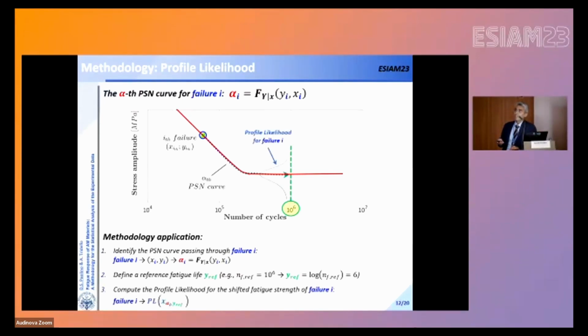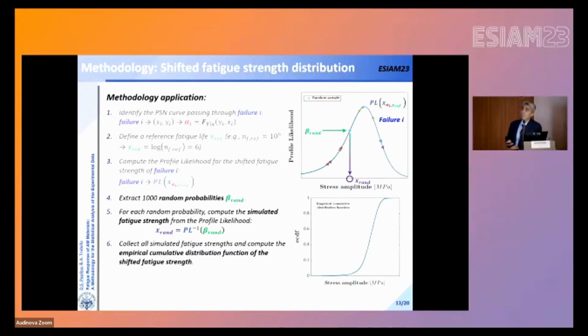And then for that reference fatigue life, you can compute, according to the procedure and the definition that I gave before, the profile likelihood function, that is this one. And it is a sort of statistical distribution of the fatigue strength shifted at this value of the fatigue life. The last three steps of the procedure are used for simulating the complete distribution of the fatigue strength for all the failure data that we have in the data set.